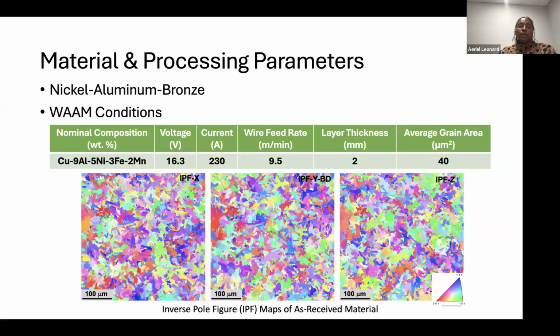Specifically, there are different variations of nickel aluminum bronze alloys. Two elements that are really important are aluminum and nickel, and iron, because they control the kappa phases that you get in the material. This specific alloy had about 9% aluminum, 5% nickel, 3% iron, and 2% manganese. This is the wire's composition for wire arc additive manufacturing.